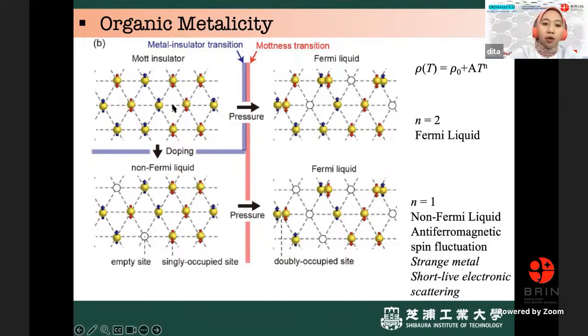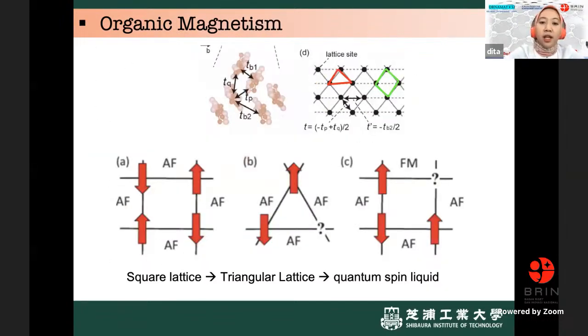Or if we dope the Mott insulating state, we can also finally have the metal like this. But before it becomes the normal Fermi liquid, it seems to be not Fermi liquid, because we found some deviations from Fermi liquid in the organic metal. So that is the charge situation. In the spin situation, the organic metals have the opportunity to tune the lattice from the so-called square lattice here, to a triangular lattice, because of the softness of the organic material.